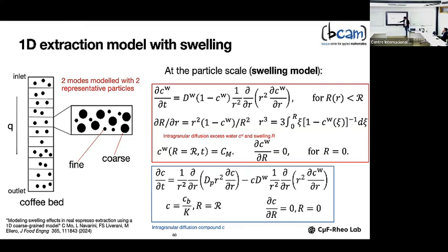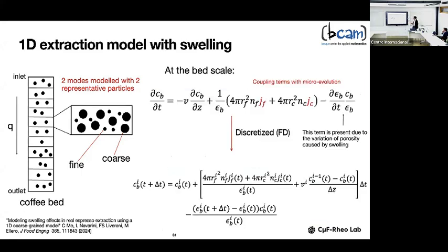This will be coupled with another evolution equation, a transport equation for the bulk concentrations that occur at the level of the bed. At the level of the bed, we use this equation here. As you can see, this is pure transport advection, taking into account the change in the porosity, because if the particles swell more, it will increase or decrease the porosity. And these are two fluxes of mass which come from the coarses and from the fines. The coarses and the fines will release some concentration of components into the liquid.